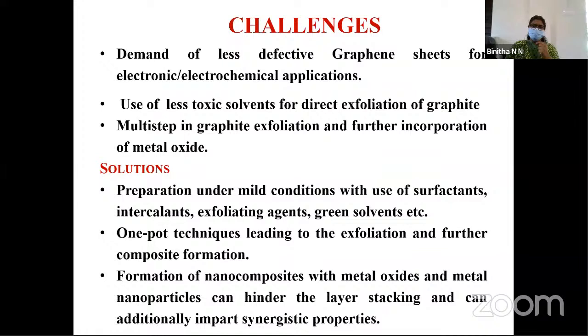But the challenges of graphene in its wide use are the requirement of less defective graphene sheets for electronic or electrochemical application, and green chemistry prefers the use of less toxic solvents for the exfoliation of graphite. Usually graphite exfoliation is a multi-step process, and we have to add another step for the incorporation of metal oxide. So the remedies are preparation under mild conditions with the use of milling agents, surfactants, intercalants, green solvents, etc. And one-pot techniques are needed for the exfoliation and further composite formation.